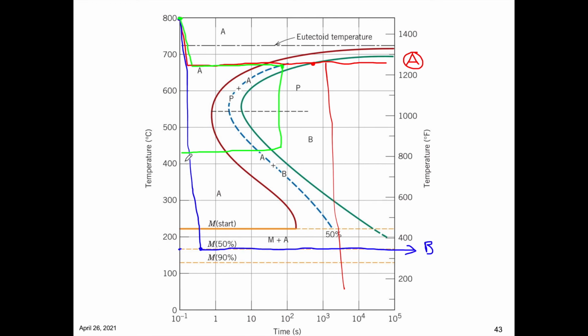So from there, we start the process over again, and we would go until we form bainite, right? So this is where we start to form bainite. But we only wanted 25%, right? So half of the remaining austenite. And so we're going to go to this point, right? So we form 50% bainite from the remaining 50% austenite, and so that's 25%, right?